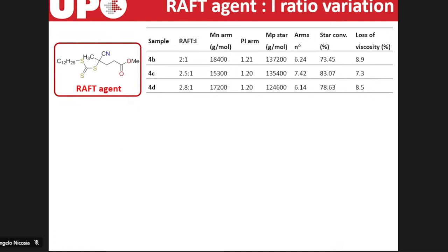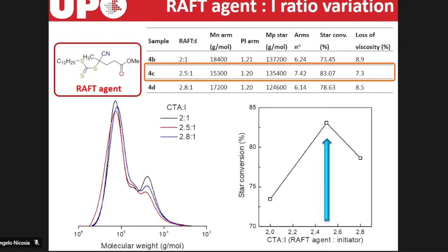Then, to increase the star conversion, we want to avoid the reversible termination at the end of the first step. So we try to optimize the ratio between RAFT agent and the initiator, and we observe that the best result we obtain is when we use a ratio of 2.5 to 1.